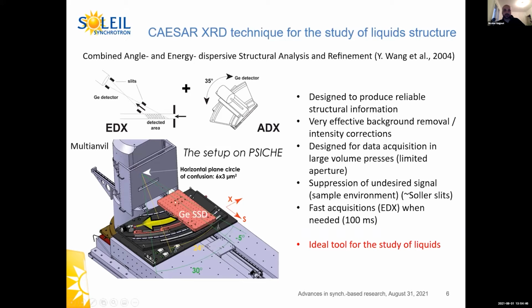And this is a very convenient and extremely interesting technique when it's paired with large volume presses, and specifically the multianvil press. It's designed to produce reliable structural information thanks to the combination of EDXD and ADX. There's a very effective background removal and intensity correction of the peaks. It's designed for data acquisition in large volume presses, as I said, because of the limited aperture of the presses, this can be a problem. There's suppression of undesired signal from the sample environment. So this acts basically like a Soller slits system, but adapted to very large equipment, like the multianvil press.